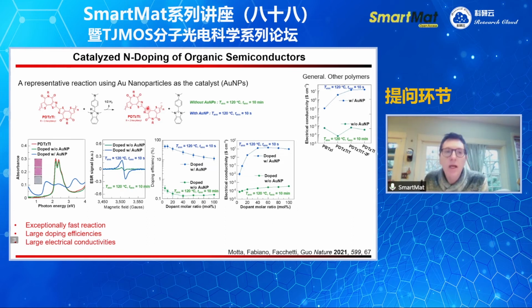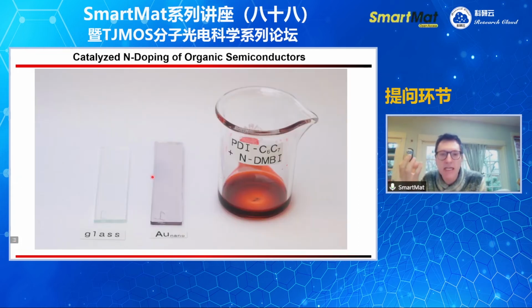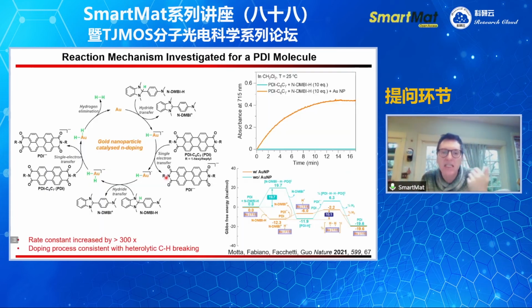For the gold particle, it can be recycled. Basically, you can take this surface after we put the solution, wash it, and reuse it. So there is a number of pieces of evidence that the catalysis occurs. We couldn't isolate any of these intermediate products at this point. I guess it could be quite difficult to do that.